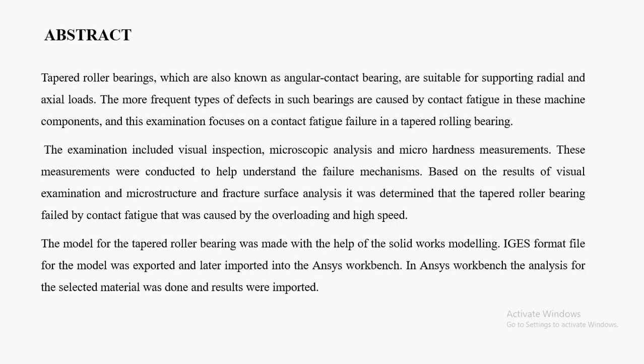Abstract. Tapered roller bearings, which are also known as angular contact bearings, are suitable to support both radial and axial load. The more frequent type of defect in such bearings occurs due to contact fatigue. The examination focuses on visual inspection, microscopic analysis and micro hardness measurement. The result of the examination shows us that the tapered roller bearing failed due to contact fatigue, which was caused by overloading and high speed.